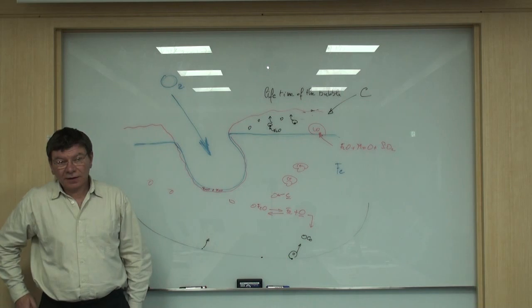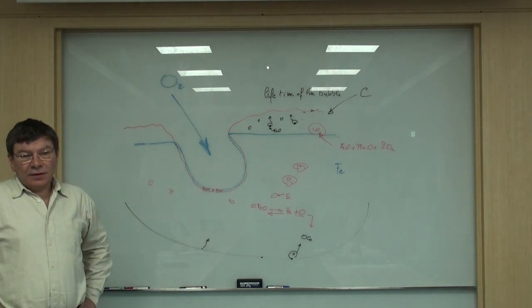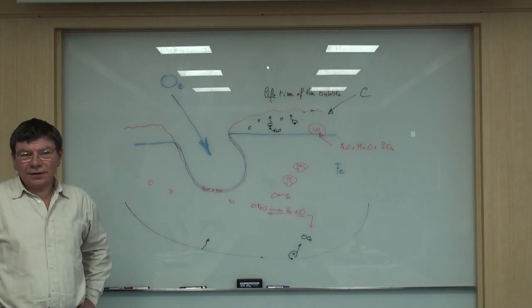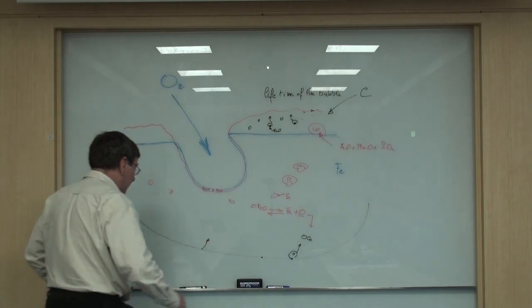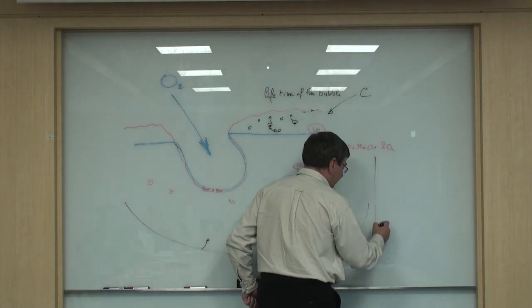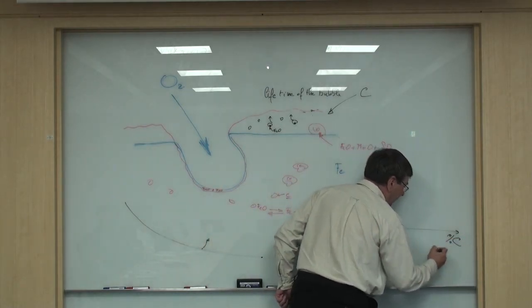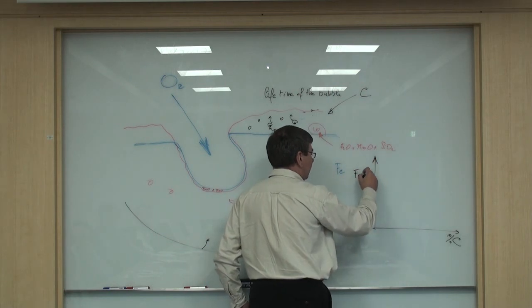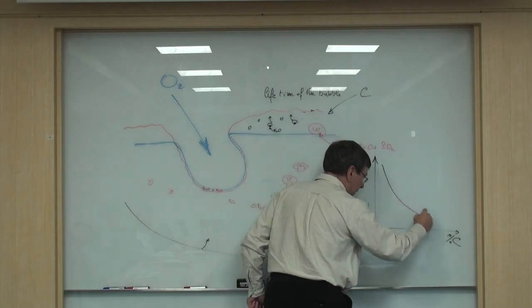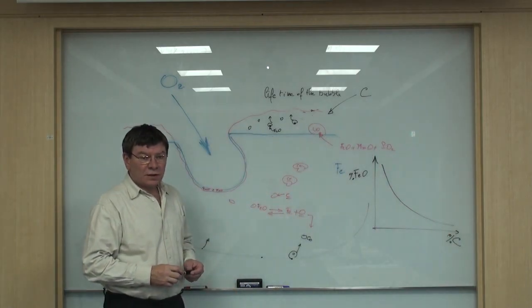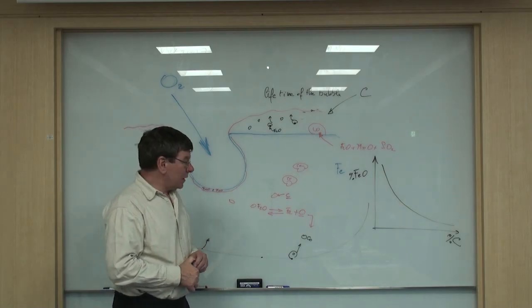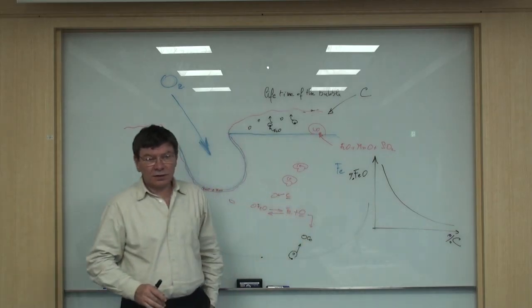Excuse me? Could you explain in more detail the relation of carbon and FeO? As you said before, as the carbon content increases, the FeO content in the slag is lower, right? I didn't say so, but something like that. You mean that if you have here the carbon content of the bath and here FeO in the slag, you have something like that. This is what you mean? Right. Yes, this you can calculate by thermodynamics.